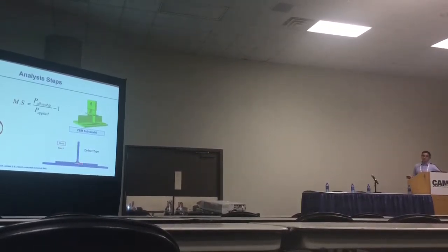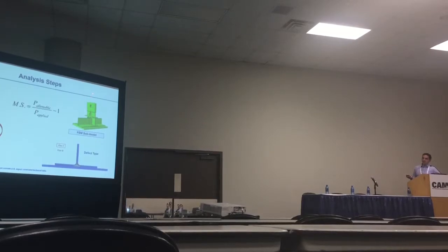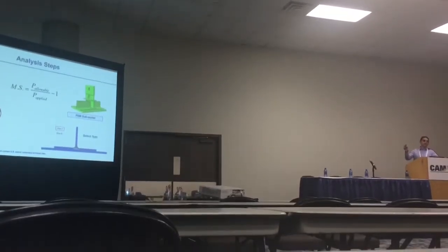For this method to work, you need to have a flaw embedded. We looked at two types of flaws: this one around the corner, and one underneath the toe filler. The reason is that those are the common locations at which a failure occurs. So we can run the simulation at both, and you pull on this model, and it keeps running until the first node releases. When the first node releases, you say this is failure. I extract the load, and that is my allowable load.